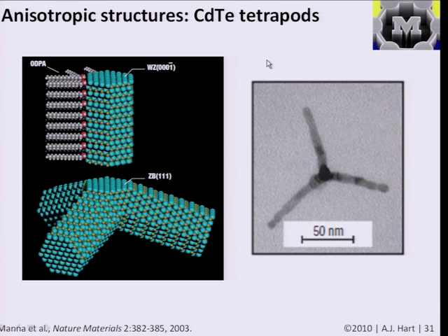And by a chemical process that's described in this paper, they find that different crystal facets of this zinc blende crystal structure are passivated by adding a certain chemical to the solution. In other words, they're able to nucleate and grow these crystals in particular directions by adding a molecule that sticks to the sidewall of the arm and prevents new monomer from adding to the surface of that arm. So you get predominant growth along these directions, and you don't get as much growth. You still get a little growth in these directions. So by controlling the conditions, you can grow these crystals that extend in one direction more favorably than broaden themselves.